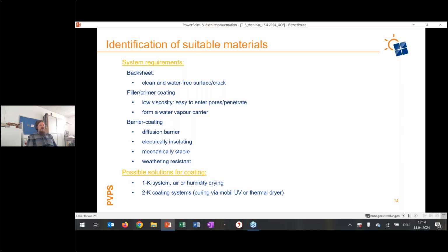So for the backsheet itself, we need a clean and water-free surface crack. The filler or the primer coating needs to have a low viscosity so that it is easy to apply and also enters the pores and the cracks and penetrates quite well. And it needs to form a water vapor barrier. And the barrier coating then needs to fulfill all the backsheet functions like diffusion barrier, electrical insulation, and